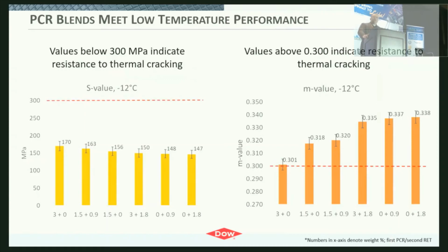One worry also is low temperature processing and low temperature performance. And so in all cases, we did meet S value. We're at borderline for the 3% recycled polyethylene only, but again, the trend here was when you start combining the RET only, you add the recycled polyethylene, it's about the average of the unmodified or PCR only versus the combination.